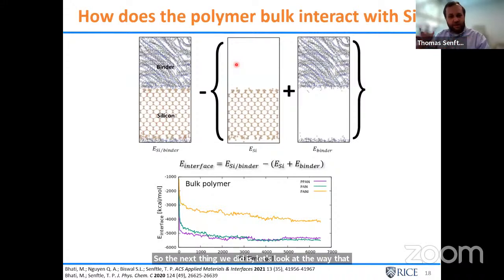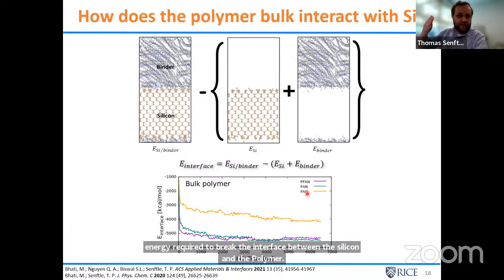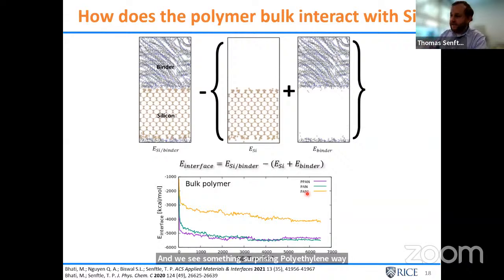So here we do the molecular dynamics to properly relax the system, allow the interface to form, and then we compute the interface energy, effectively the energy required to break the interface between the silicon and the polymer. And we see something surprising. Polyaniline, where the single chains would bind the strongest, binds the weakest if it's in bulk form. So we get this reversal in the trend of the binding energy.